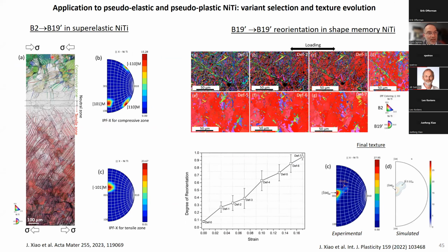It's superelastic, so it was maintained in bending condition. Here I have a contraction. Here I have an extension part. And you can see the colors of martensite that is formed here inside the austenite are completely different. So we can calculate them, and we can predict actually that the variants that will be formed are the red one here, and the variants that will be formed are the green one there. It's a completely different orientation relationship. It is very well explained by the interaction work.